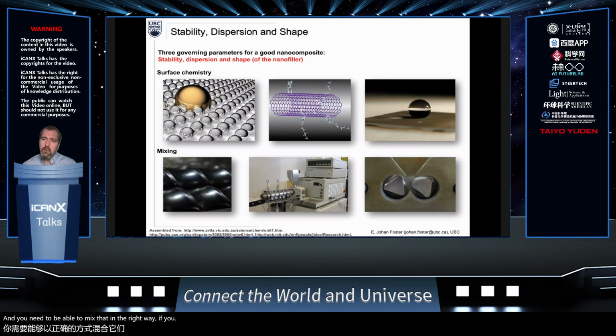If you can't get your cellulose nanocrystals throughout that polymer, then that becomes problematic. Okay, so stability, dispersion, and shape of your nanofiller is very important. If you can control that, if you can get that dispersed into your polymer, you can get a smart material. You can get a reinforced material. So I set up all that, and I will change gears for one last story.